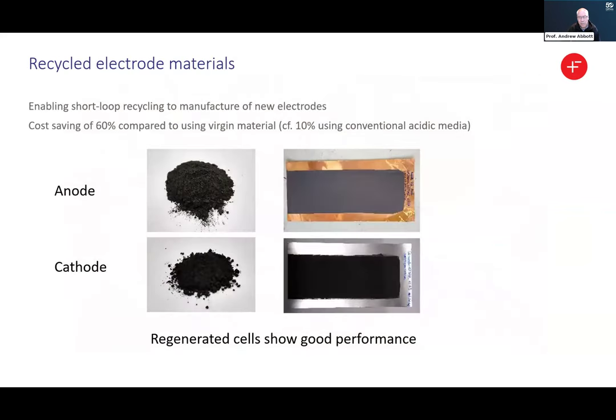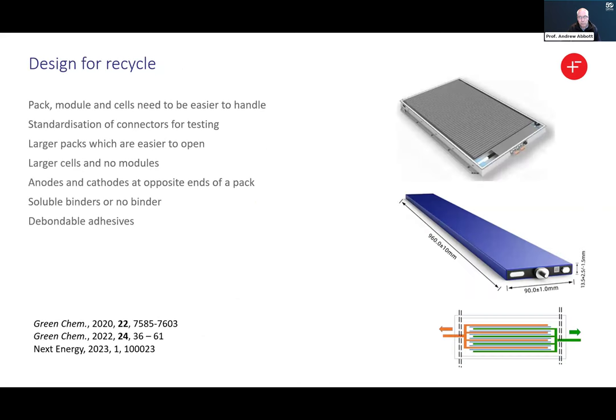We can then take that material, and in under an hour between getting material, we can cast it into new electrode materials. We've even done it with production scrap, where we've just reactivated the current binder that's on there and recast it. So we think that you can get a cost saving of typically sort of 60% as opposed to using virgin material, and around about a 10% cost saving just using traditional acidic media.